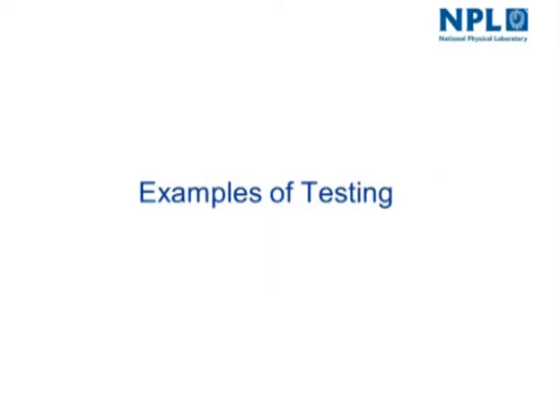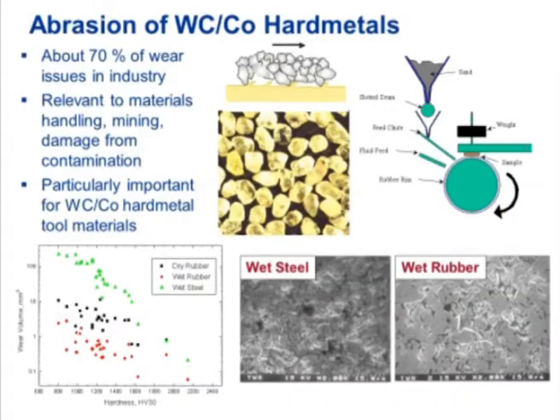Right, yes. I just wanted to make the talk a little bit more exciting, from my point of view and hopefully from yours, by looking at a couple of examples of the sorts of things we've been doing more recently. One of these is a little bit older now, but it illustrates that even in abrasion, and you can see this diagram here, you've got a loose bed of abrasive particles that's pushed against the surface and causes wear. As I said, about 70% of wear issues in the industry are due to abrasion. We're looking at wear of tungsten carbide, cobalt, hard metals here. It's relevant to materials handling, mining, and so on, and tool materials from hard metals is a particularly important issue.